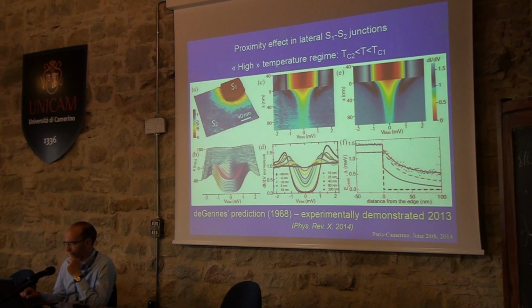Next slide, please. In the next slide, I show exactly the same situation, but at the temperature at which the superconductivity in the wetting layer is suppressed. However, the fact that this material is not really a normal metal, but a material in which you have superconducting fluctuations, leads to a special evolution of the proximity effect, which is different from the pure case of superconductor normal metal. Unfortunately, I have no time to stop more here, but in the bottom, you have a reference. It's a recent PhysRev X paper we just published, and we clearly account for this induced superconductivity in the neighboring layer between this large superconducting island and the material which will become superconducting at low temperature.